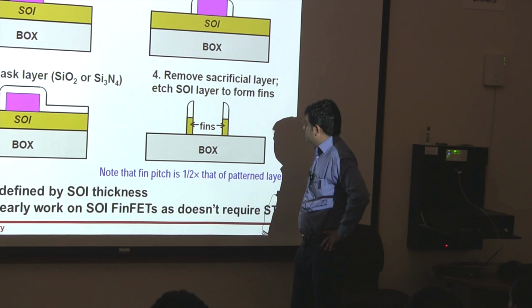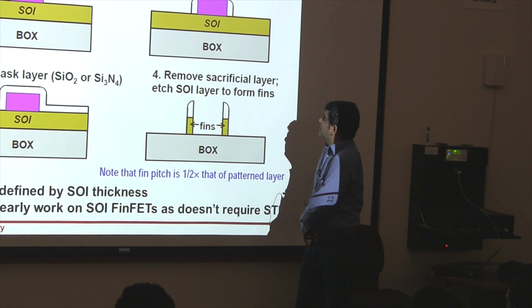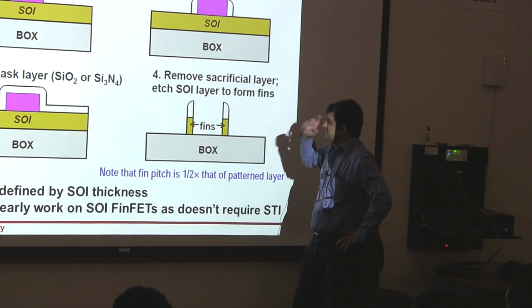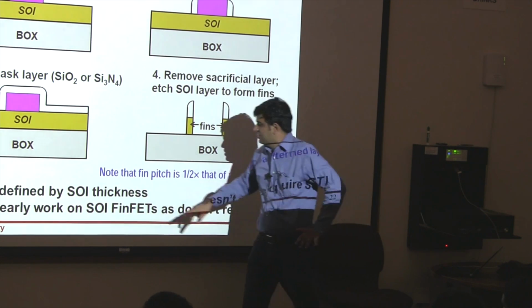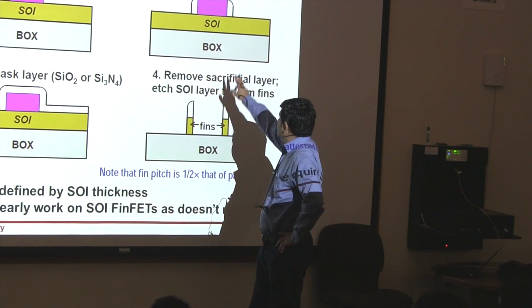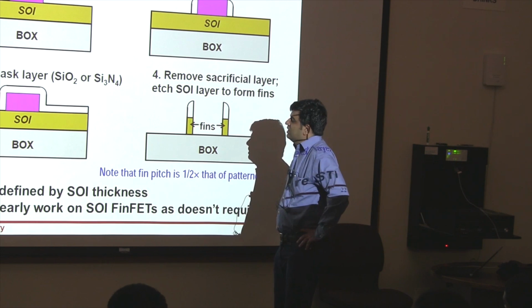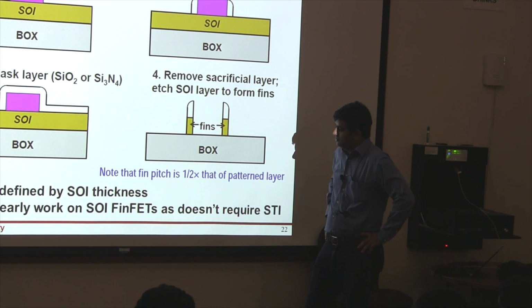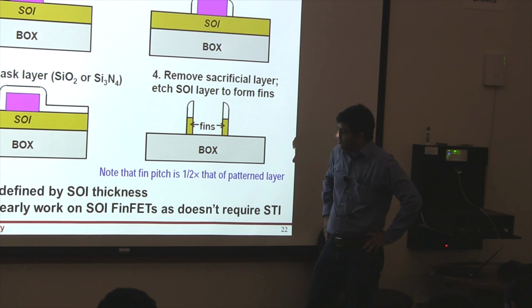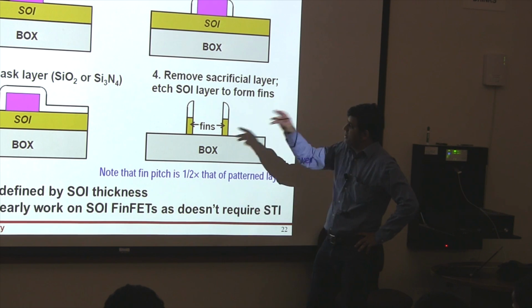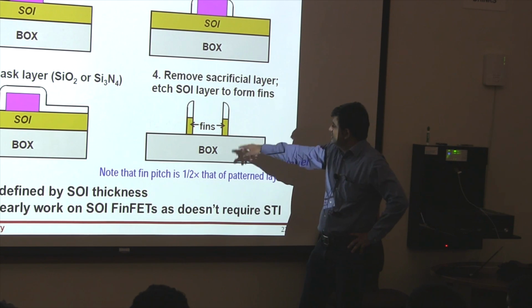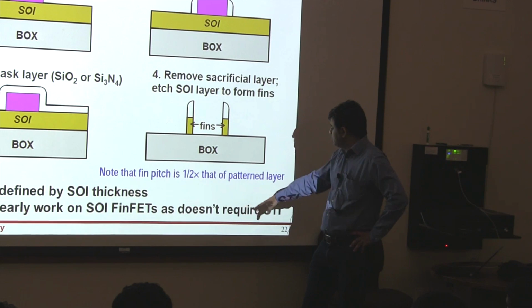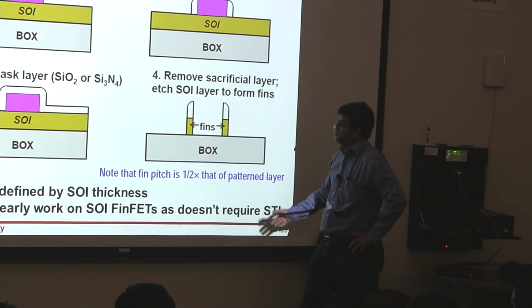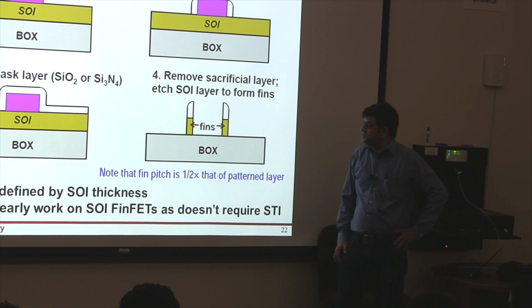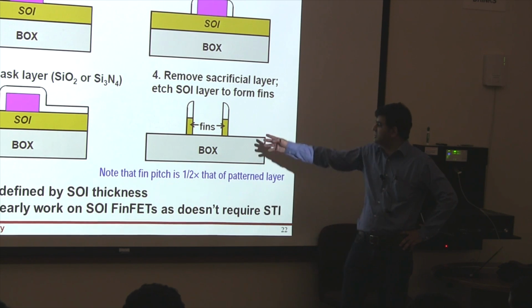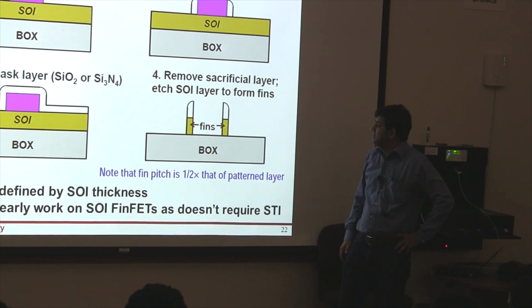So the height of your fin is essentially predetermined by how thick that SOI layer to start with was. So it has that advantage that the height of your fin is determined by the thickness of your SOI layer instead of being defined by your etch process, which can introduce variability. And a lot of early work on FinFETs was all done on SOI FinFETs, because it's easier to define these fins, and it's very hard to do an STI process in a university lab. I don't know any university, at least in the US, which can do that other kind of process, but it's much easier to define fins this way.